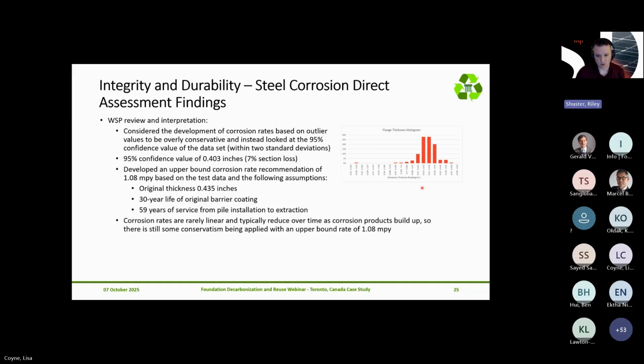So we developed our upper bound corrosion rate recommendation based on the original pile thickness shown here, 30 years of service life of the original barrier coating, and then a total 59 years of service from pile installation to extraction. And we get a value that's approximately 1.08 mils per year.